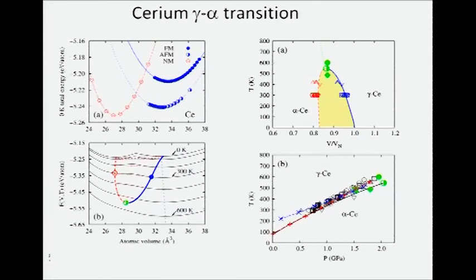Until here, we got the critical temperature. It turns out this is quite amazing - we got about 2 GPa at the critical point between the gamma phase and the alpha phase, with the correct temperature and slope, everything written in terms of volume. So this is our result for cerium. I showed the model result - I think we solved this problem.